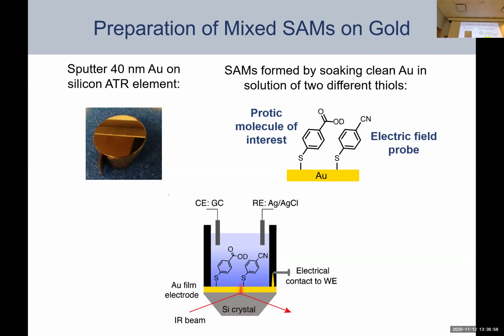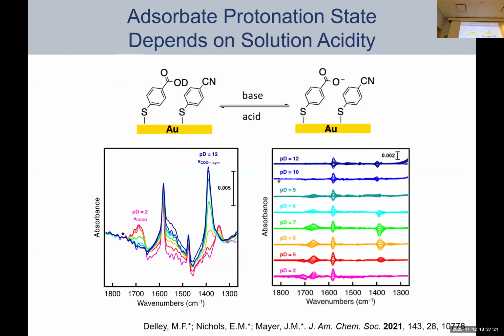Okay, and all of these experiments are going to be done in aqueous electrolyte. The reason I'm drawing OD here is because we're using deuterated water, D2O. The reason for that is because the bending mode of water, this delta mode of water, perfectly overlaps where all the signal of interests are for the carbonyl and the asymmetric carboxylate stretch.